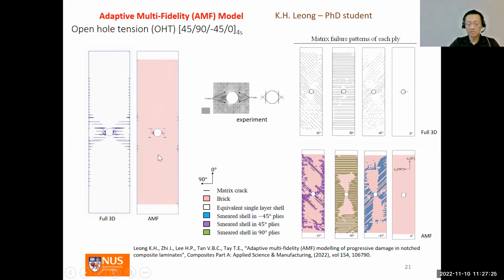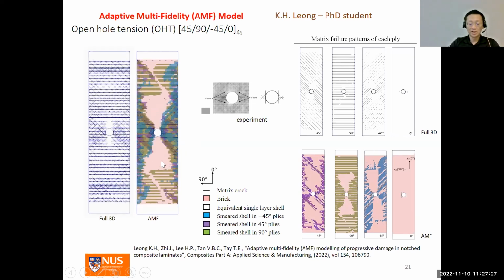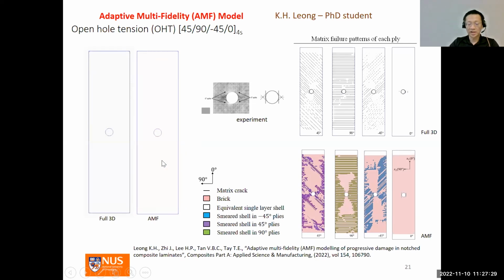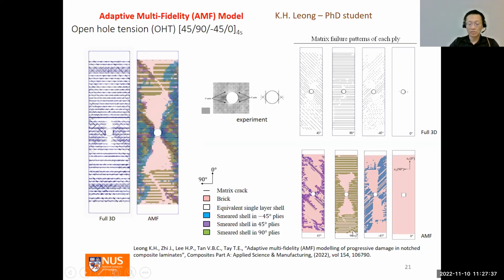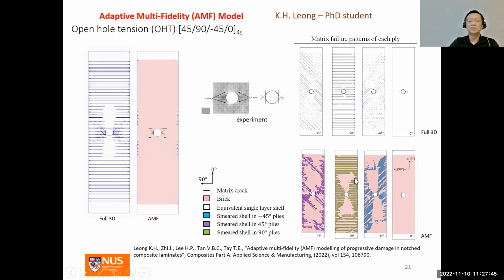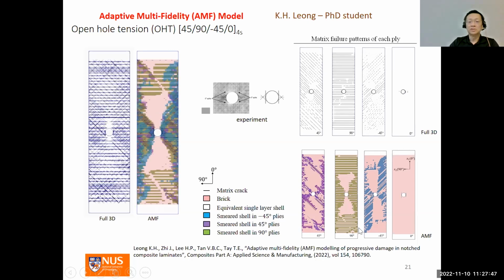And then when the micro cracks become saturated, the region is then converted back to shell elements with smeared crack properties. And that's denoted for each ply with the different colored regions. So for example, here, the 90-degree ply, the smeared regions are denoted in green, the -45s in blue, and so on and so forth.